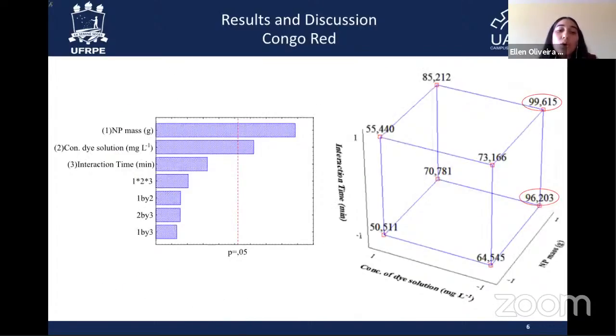Starting with the Congo red, we have the Pareto chart that exposes the factors and their significance at 95% of confidence. And for the values presented, we can see that only the nanoparticle mass and the concentration of dye solution are significant. As for nanoparticle mass, we can say that it was expected since the adsorption intensity is proportional to the specific surface area, and adsorption is a surface phenomenon. The greater the number of adsorption sites, the greater will be the percentage of adsorption.